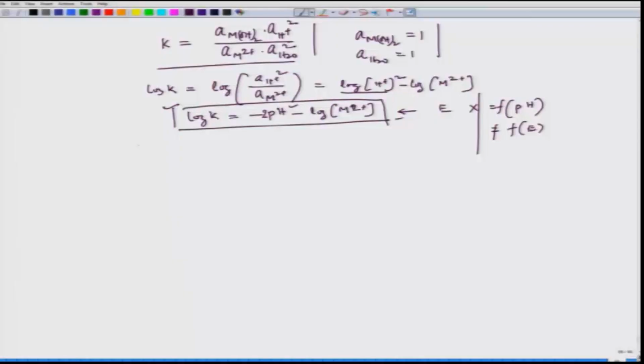Now, interestingly, the Pourbaix diagram will not be complete if we do not consider 4 reactions involving only oxygen, dissolved oxygen of course, hydrogen, hydrogen ion, and 2 other species which are OH minus and H2O. So, now we can have 4 more reactions involving H plus, OH minus, O2, H2O, H2.